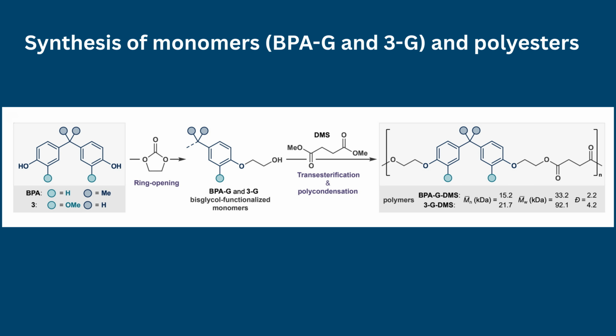Polymer synthesis and material characterization. Among the top candidates, BGF was selected for scale-up and polymer integration due to its favorable synthetic yield and safety profile. To facilitate polycondensation, BGF was converted into a bis-glycol ether derivative via reaction with ethylene carbonate. Polyester synthesis was achieved through polymerization with dimethyl succinate, a potentially bio-based diester, yielding a novel material, BGF-based polyester, alongside a BPA-derived analog for comparison.